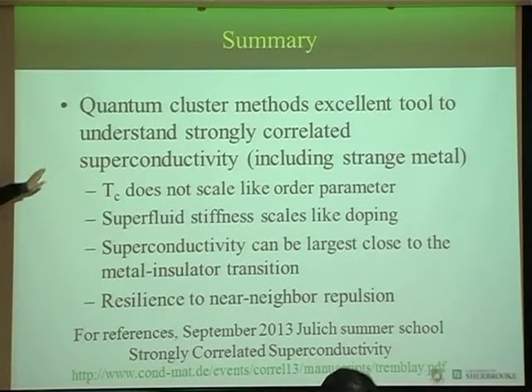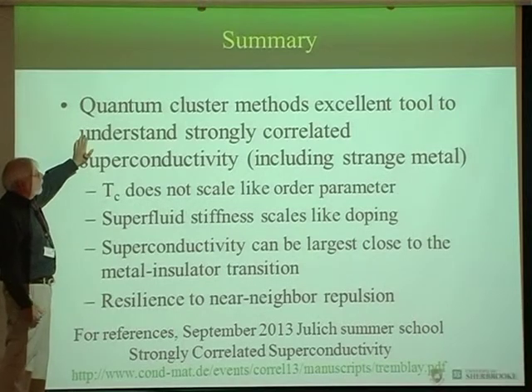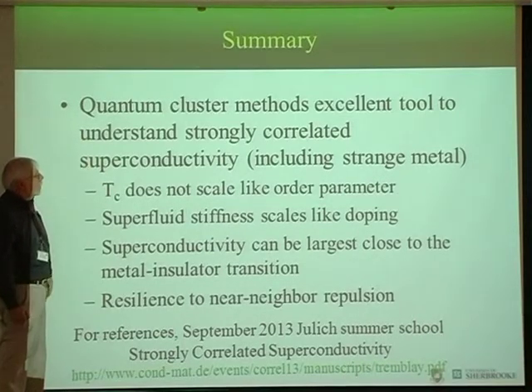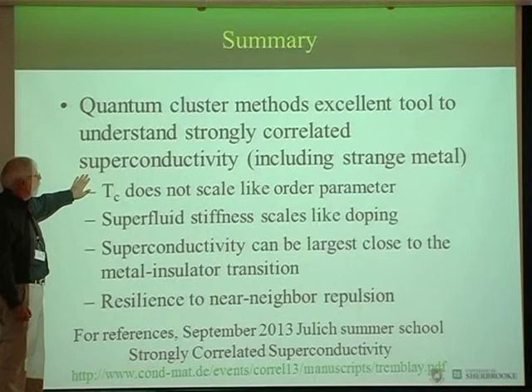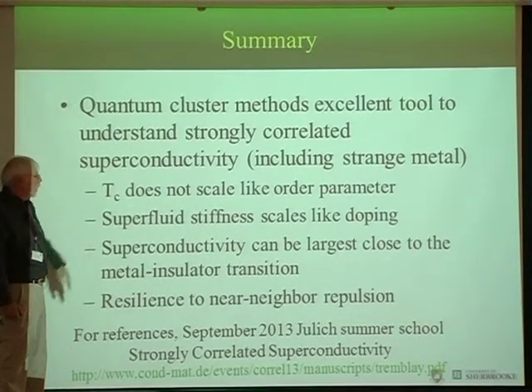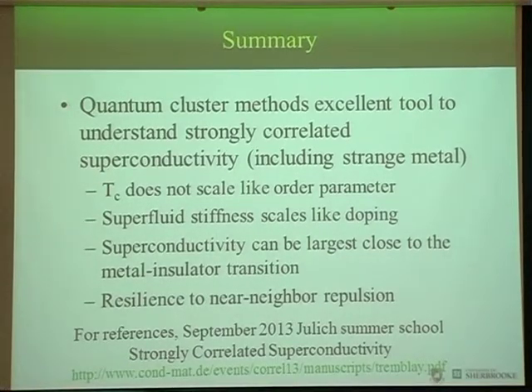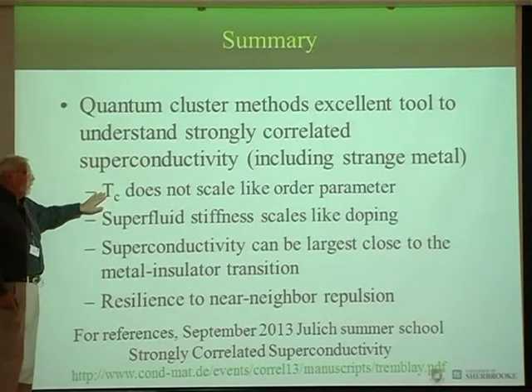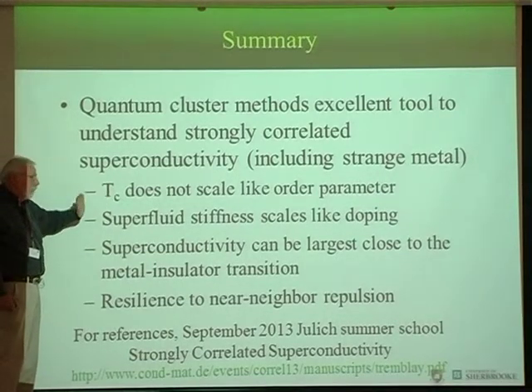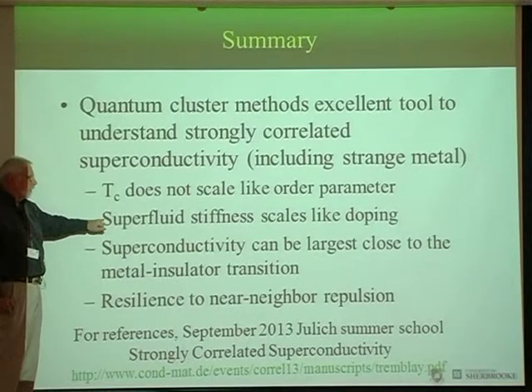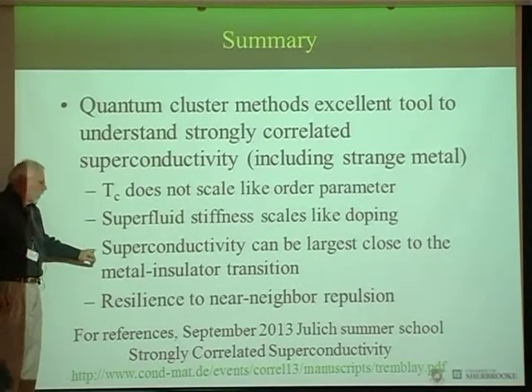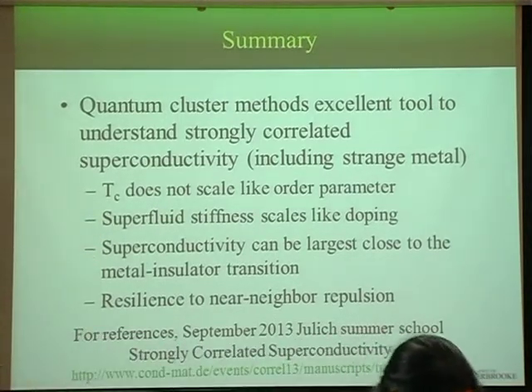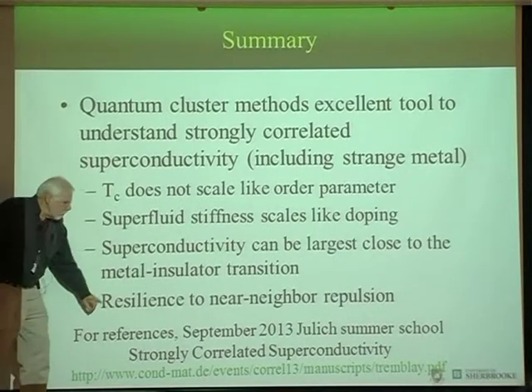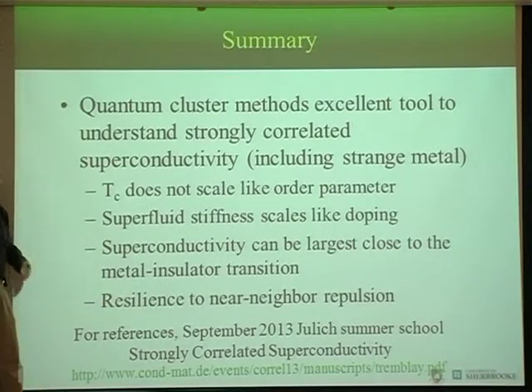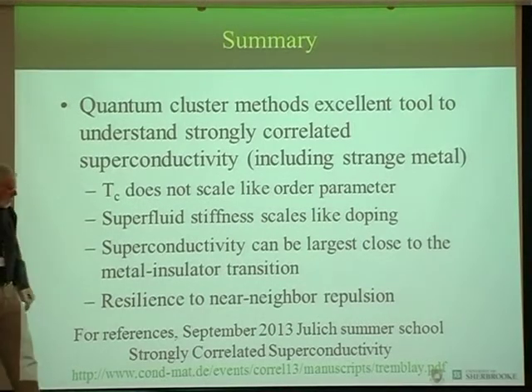So quantum cluster methods, generalizations of dynamical mean field theory, are excellent tools to understand strongly correlated superconductors, including the strange metal, which I didn't have time to show. TC does not necessarily scale like the order parameter. We have results for this, but I haven't shown them. Superfluid stiffness scales like doping. Superconductivity can be largest close to the metal insulator transition. And this resilience to near neighbor repulsion at strong coupling is very important.